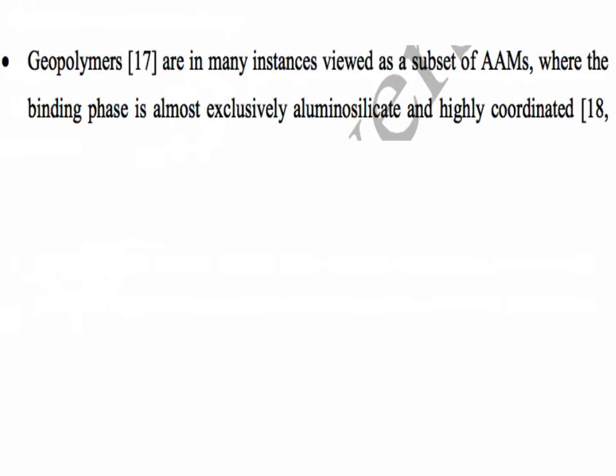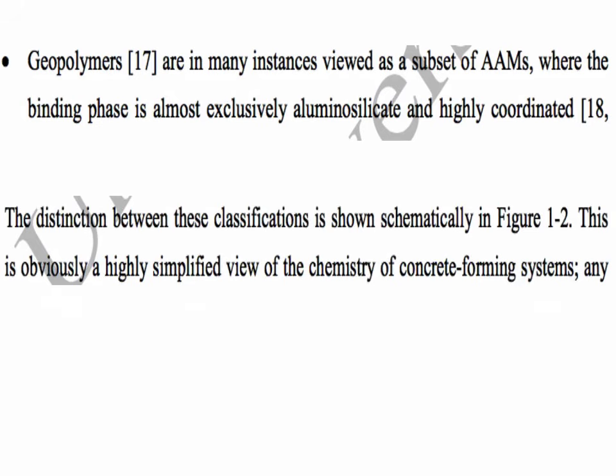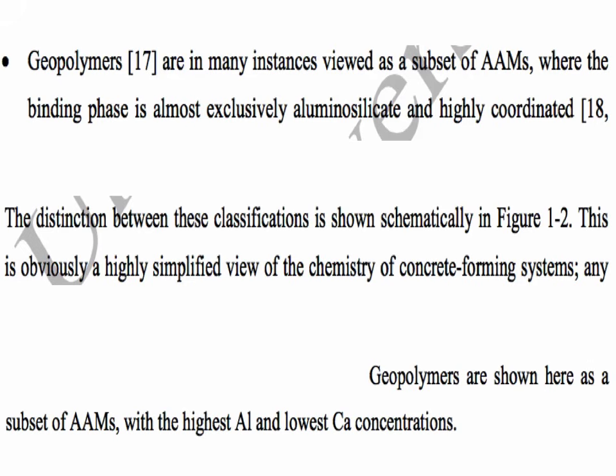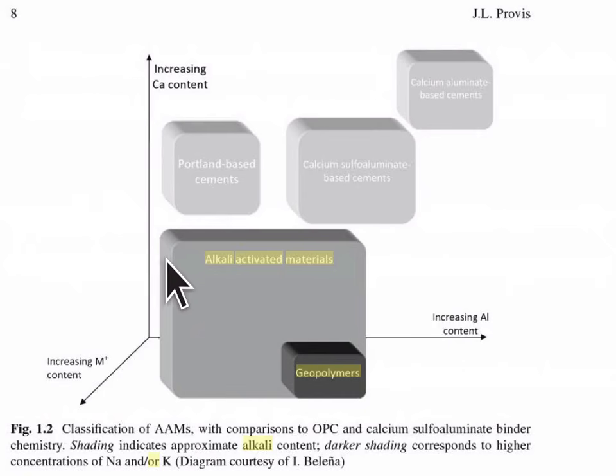Geopolymers are in many instances viewed as a subset of alkali activated materials, where the binding phase is almost exclusively aluminosilicate, and highly coordinated. This distinction between this classification is shown schematically in figures 1 and 2. This is obviously a highly simplified view of the chemistry of concrete forming systems. Geopolymers are shown here as a subset of alkali-activated material with the highest Al and lowest calcium concentrations. So you have the domain of alkali-activated materials, the big one, and you have the small domain of geopolymers.